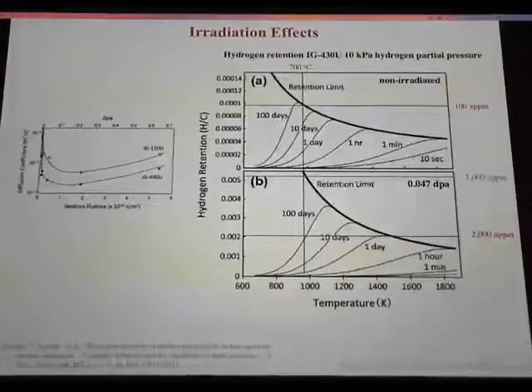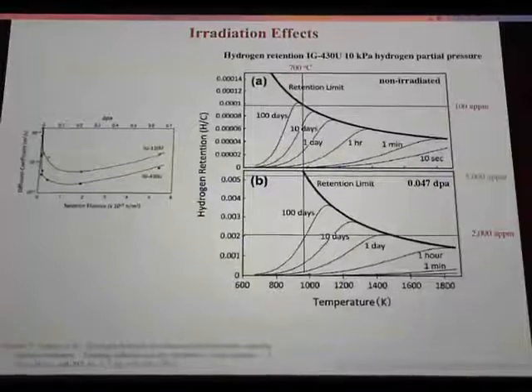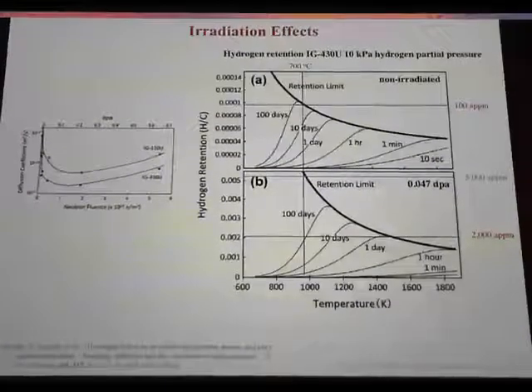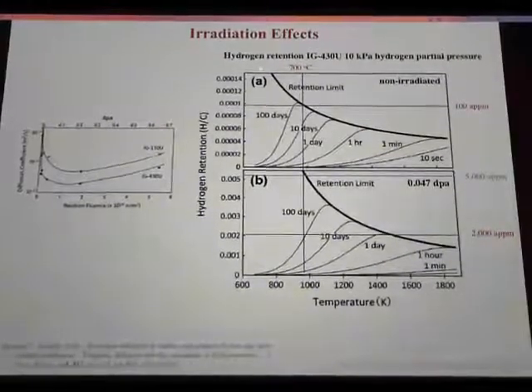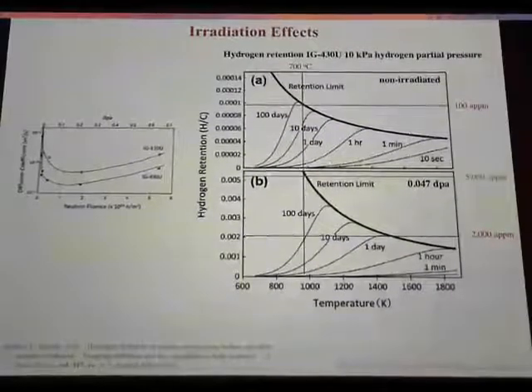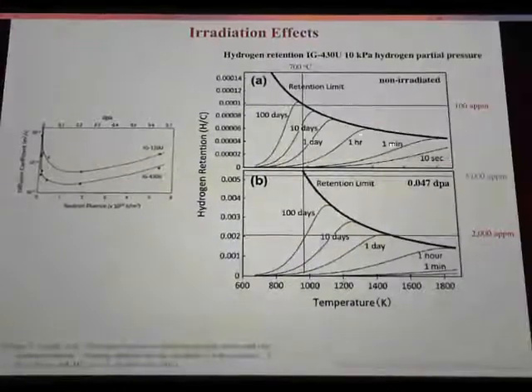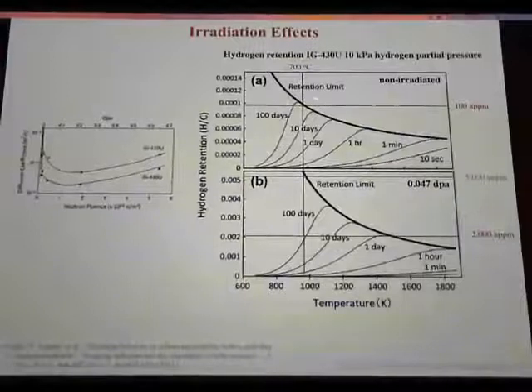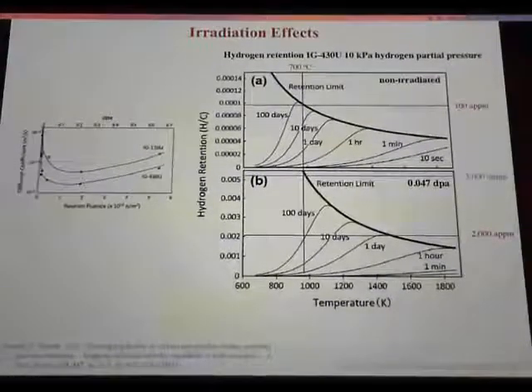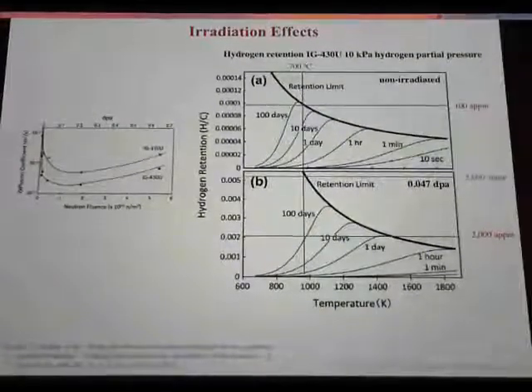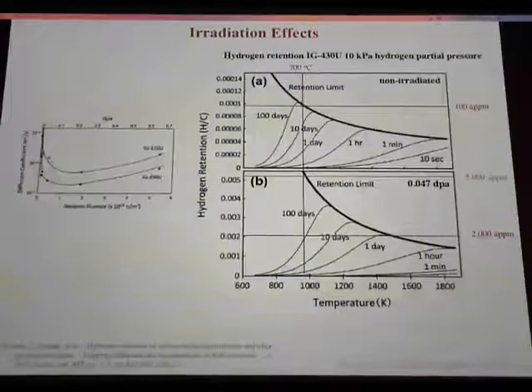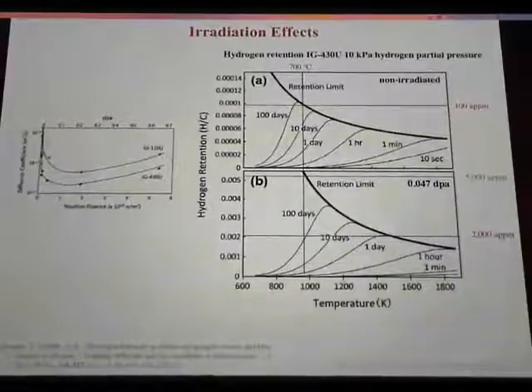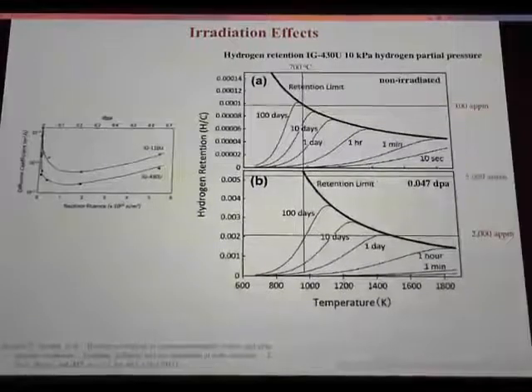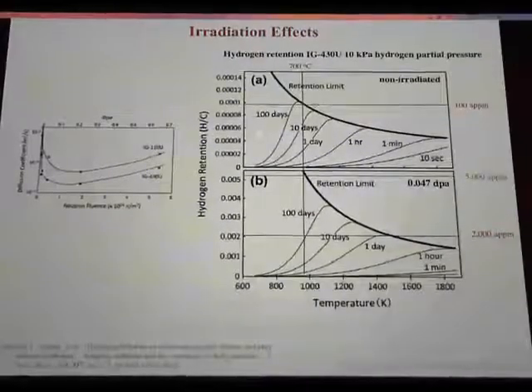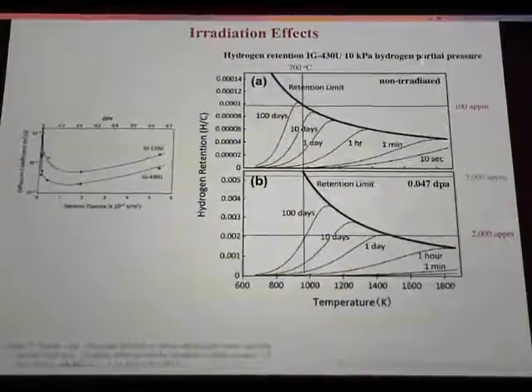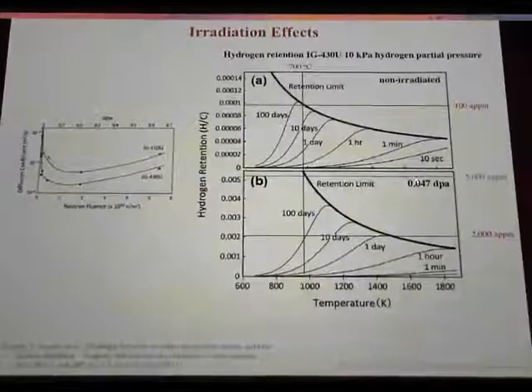Now how fast is also important. So we can't treat the graphite as a point absorber. The time of absorption into the graphite is also important. So here's an example of non-irradiated graphite exposed to hydrogen for 1 minute and then for 100 days. And so you can see that the hydrogen uptake goes up by an order of magnitude in that time. And so the time it takes for a graphite sample to load with hydrogen is on the order of days, tens of days, hundreds of days. So if you have a graphite pebble traveling through the core, we can't assume that it instantaneously sucks up the tritium, that it instantaneously gets to thermodynamic equilibrium. We need to understand the time evolution as well. And then that time evolution changes with irradiation. So that's non-irradiated, that's irradiated.